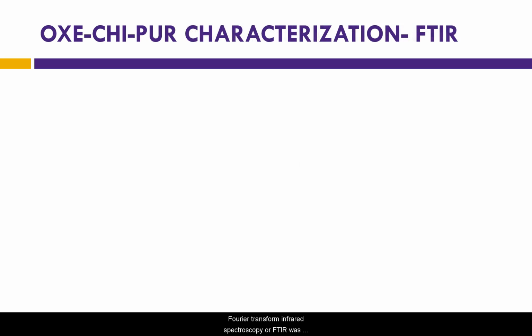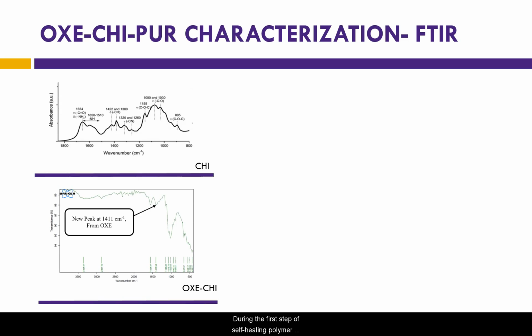Fourier transform infrared spectroscopy, or FTIR, was used to evaluate the synthesis of the self-healing polymer by comparing the obtained spectra of chitosan with the oxetane-substituted chitosan, as well as the spectra of HDI with the final product. During the first step of self-healing polymer preparation, chloromethyl oxetane was reacted with chitosan in order to attach the oxetane ring to the OH group of chitosan. The FTIR spectra of chitosan and oxetane-substituted chitosan confirmed the mentioned reaction. The new peak observed at 1411, but only on the FTIR spectra of oxetane-substituted chitosan, corresponds to CCH3 of oxetane, thereby confirming the successful reaction of oxetane and chitosan.